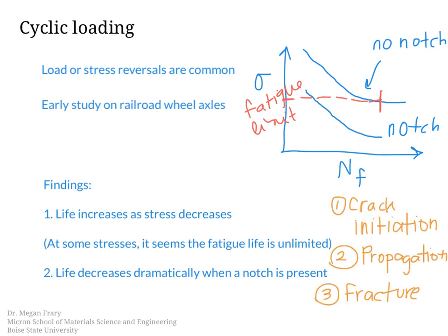And those three steps are crack initiation, so the crack has to first form, then crack propagation, and then fracture. And so the fact that there is a notch present, that would dramatically increase the rate of the crack initiation stage.